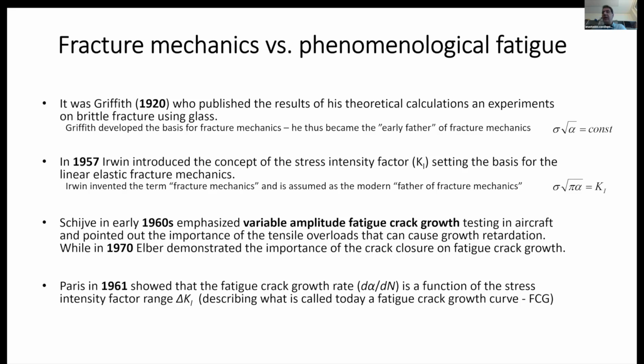emphasized the testing of aircraft based on variable amplitude loading. You will also see a gradual change from continuous loading to variable amplitude loading, and this is because of the change in the machines and the controllers. Until 1950, 1960, we couldn't do complicated loadings. We didn't have the computational possibility in controllers and machines to control variable amplitude loading. That's why you cannot find these types of loading earlier. Only after the 1960s, 70s, we see the first publications on variable amplitude investigations. And then here I also have 1961, where Paris introduced the fatigue crack growth rate in fracture.